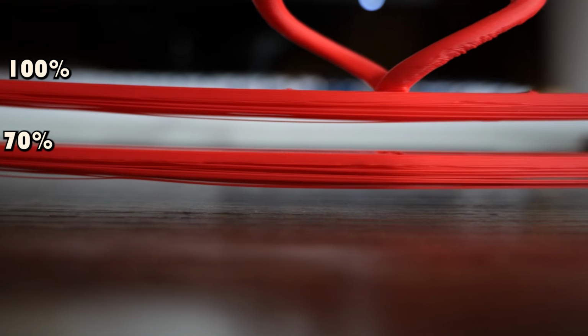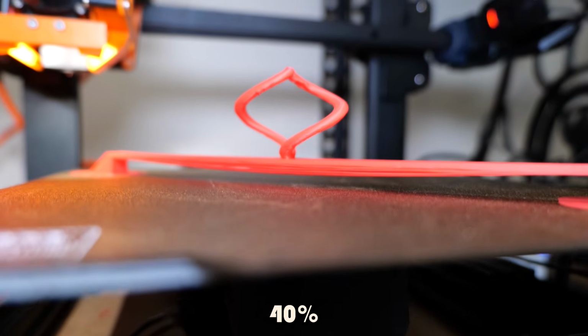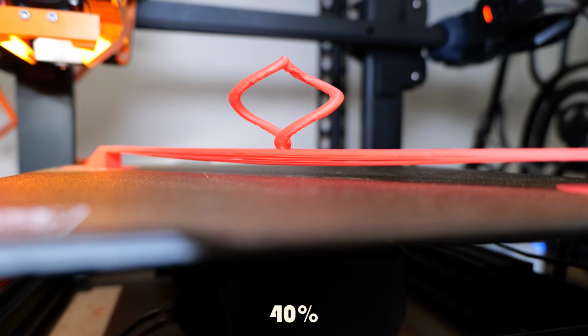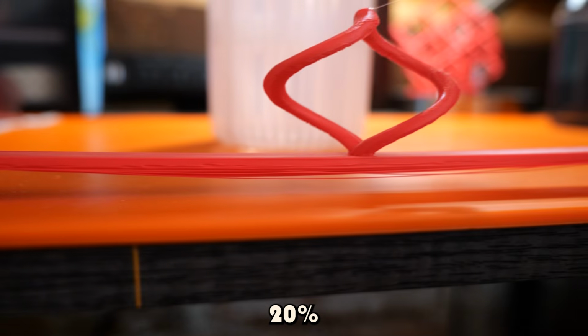I also ran a few more of those cool bridges at 70%, 40%, and 20% fan speeds to check out how the bridging would do at different speeds. I'd say that the 70% and 40% looked pretty similar to the 100% fan speed one, but the 20% fan speed is where it starts to fall apart.